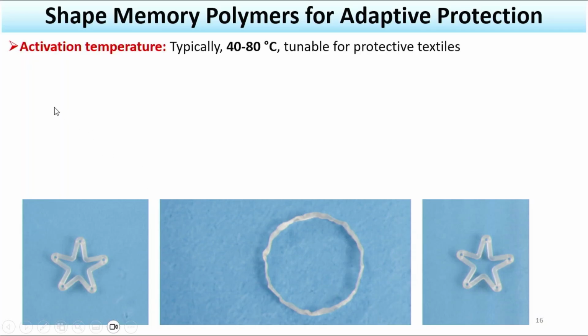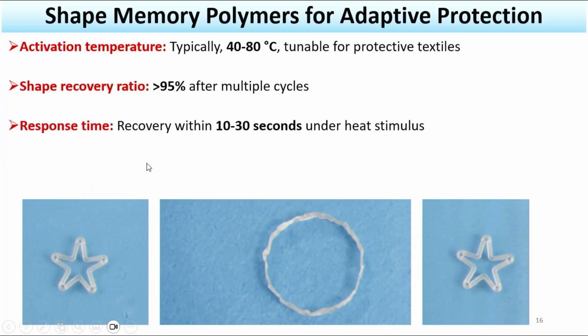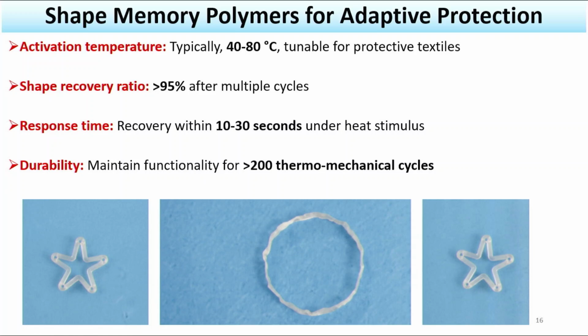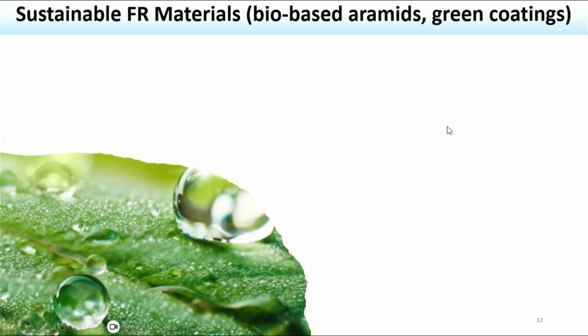So, activation temperature is typically 40 to 80 degree Celsius, tunable for protective textiles, okay. Shape recovery ratio, it gets recovered more than 95%. Response time is within 10 to 30 seconds, as the shape gets changed. And durability: it has been observed that over more than 200 thermomechanical cycles, it maintains its performance.